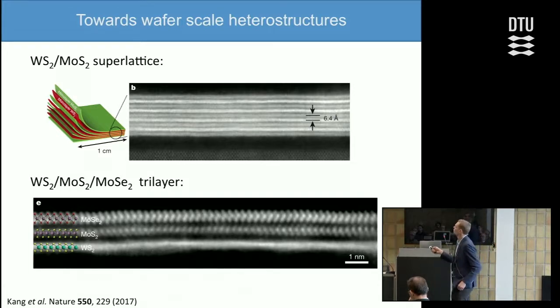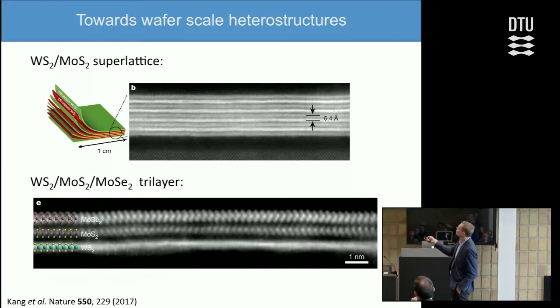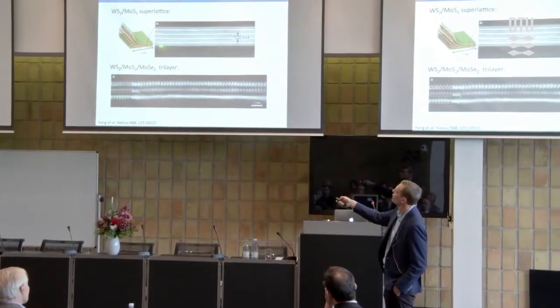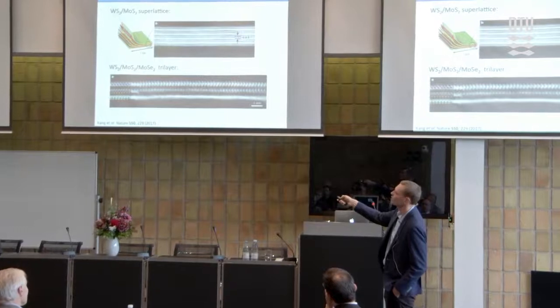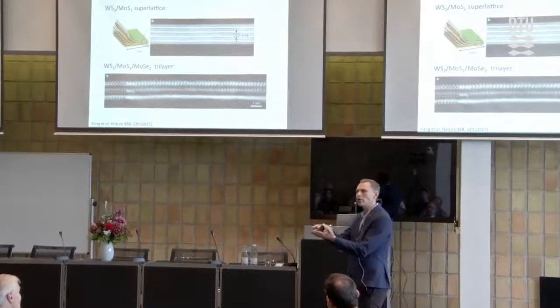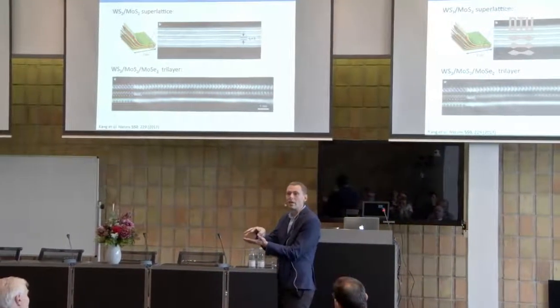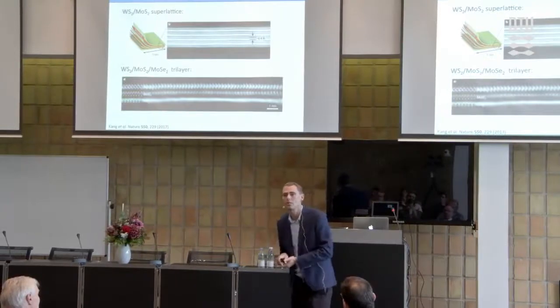But for these types of materials, lattice mismatch is not a problem. The reason is that the materials themselves are chemically inert, and therefore they don't form covalent bonds in the third dimension. You can see these in this TEM picture, a transmission electron microscope picture. You can see black lines in between, and that's because the bonding between the layers is weak. This is called van der Waals bonding, and thus the name van der Waals heterostructures.